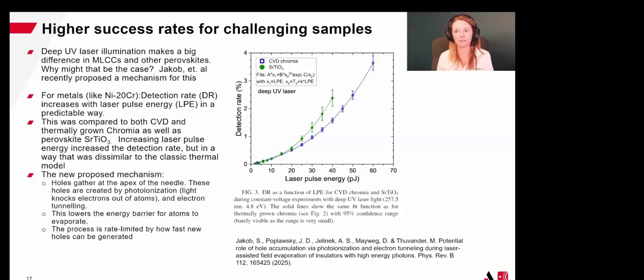And what they really found is that increasing your laser pulse energy caused your field evaporation or detection rate to proceed in a way that wasn't quite the same as it did for metals. So there must be something else going on rather than just a shot of thermal energy, which would directly relate into field evaporation. So the authors propose that this might be related to photoionization because these materials have band gaps which are closer matched to deep UV compared to UV.